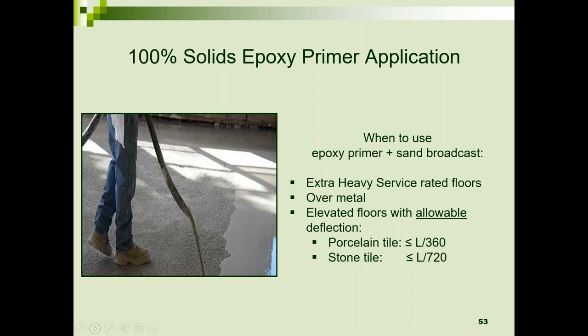As far as epoxy primer, that's best used when you have an extra heavy service rating floor. TCNA describes what an extra heavy service floor is. It's also used if you're installing underlayment and tile over a metal surface, or you have elevated floors that exhibit allowable deflection. So an epoxy plus a sand broadcast, and the sand broadcast is done to allow a better bond of the underlayment materials over it.